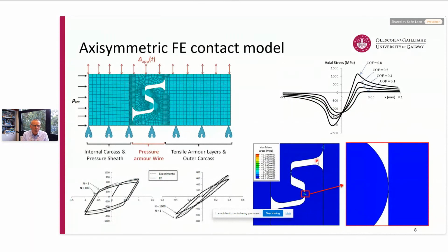Now, there's a range of different models used, but one of the first models we started to work with was a fairly simple axisymmetric FE contact model. We'd had a lot of experience with contact modeling. So, the main thing here is to try and capture some of the various layers within this flexible riser, not just the pressure armor wire, and to capture some of the loading. So the applied tangential displacement, which is the delta applied in the vertical direction there, internal pressure, external pressure isn't labeled there, but it's captured in the model as well. It's included in the model.